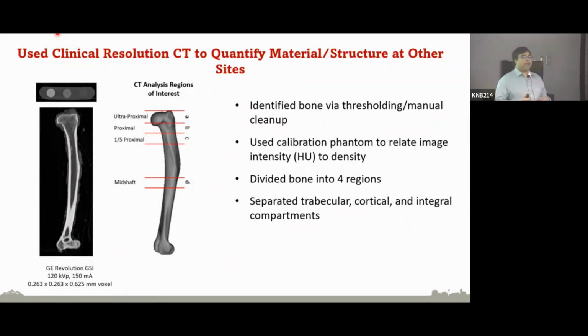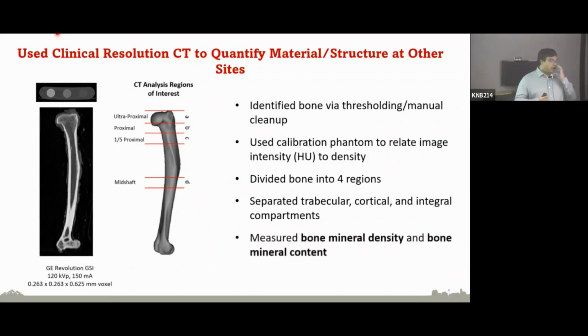It's a calibration phantom. It's basically an object that has 3 little rods of known mineral density, and we're able to relate the CT intensity, so the color or the brightness of these rods, to an actual density value to assign to our bone. After that, we divided our bone into 4 different regions: the ultraproximal, proximal, 1/5 proximal, and midshaft, and then further subdivided those into cortical, trabecular, or integral compartments. Just like before, our key measurements here were bone mineral density and bone mineral content.